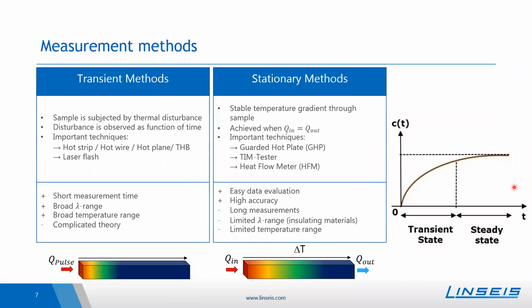Additionally, the steady state methods have a rather limited thermal conductivity range, so it is more focused on insulation materials. Probably some of you know the guarded hot plate method or the heat flow meter, which are the typical steady state methods. And also our TIM tester belongs to this group of methods. Advantages with the steady state methods is that the data evaluation is rather easy and one has a very high accuracy because one really waits until everything is stable and then reads out the values.